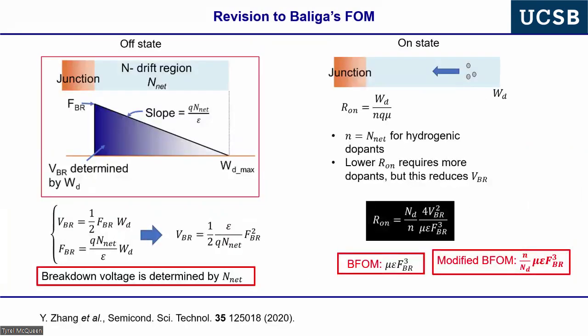And so the way you derive this is essentially just an exercise in Gauss's law, okay? And so from Gauss's law, the slope, if you deplete a semiconductor, is given by essentially the net doping, okay? And so this is going to be usually n-type. And net refers to the concentration of donors minus the concentration of unintentional acceptors. And then usually you work with a triangular field, which means there's actually curvature, okay, if you look at the band diagrams. And so this is fine, and this means if we want to go to very, very high voltages, okay, this is electric field versus distance, and so this is how you get to the voltages, and you go through a little bit of arithmetic, and you come up with these equations.